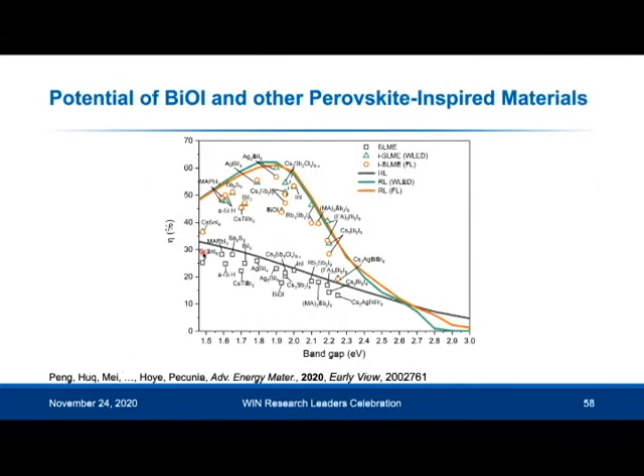And we wanted to see what the future potential is for this material. And we calculated that if all the indoor light was absorbed by the BiOI and converted to charge, we would have an efficiency that would reach 44%. We also looked at a wide range of other perovskite-inspired materials, and we showed that these materials, because they have band gaps close to the optimum for indoor PV, could reach efficiencies within the 40 to 60% range in the future.